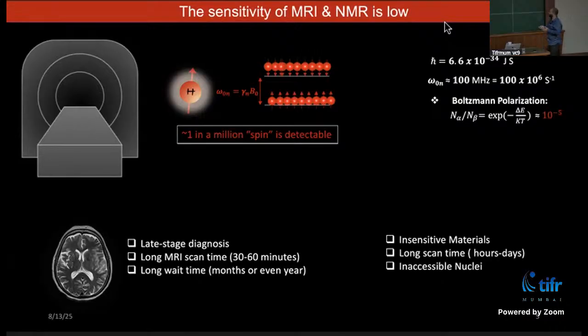For NMR, there are many materials which in principle can be probed with NMR, but we cannot probe them just because of sensitivity. And if one wants to distinguish the signal from the surface compared to the bulk, NMR is not a very good technique in the conventional form. That is because the number of atoms or spins on the surface is a lot less than in the bulk.